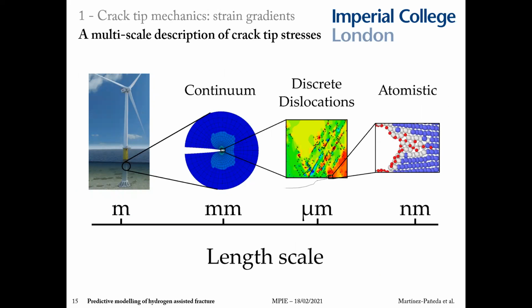So I will start first with this key aspect of the importance of resolving properly your crack tip stresses. And the key step here, or I guess in any research problem, is to identify what are the critical variables of your problem. In this case, hydrogen concentration and stresses, and also what is the critical length scale. There's an obvious trade-off between computational cost and precision. We're still very far away from being able to use discrete dislocations or atomistic approaches to model real components. But if all the interesting things are happening in the first 3 atoms ahead of your crack tip, then your efficient continuum model is not going to have enough resolution to resolve the physics of the problem. So I guess the question here is, what is the critical length scale for hydrogen embrittlement?